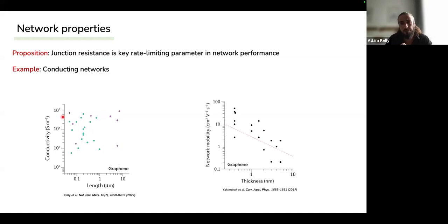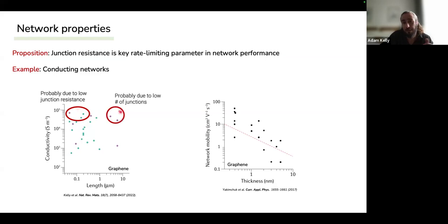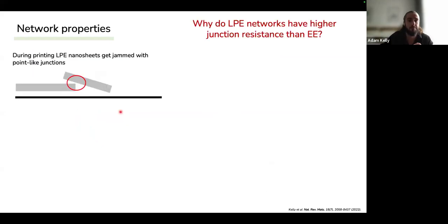So we found this paper here, which is interesting because they showed that the thickness of the nanosheet is far more important. The mobility of the network actually decreases as the thickness of the nanosheet increases. So if you go back to the length, this is probably due to low junction resistance because of their thin nanosheets. And this one's probably high conductivity because there's probably just a low number of junctions between the electrodes. So what is this about? Why do LPE networks have a higher junction resistance than the electrochemically exfoliated ones?